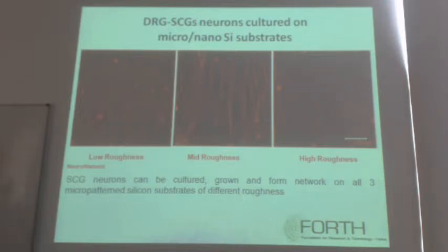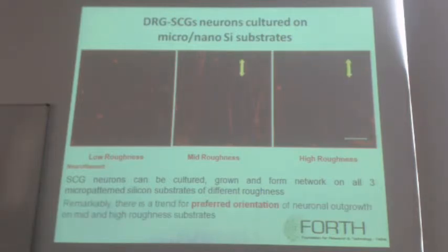So the next step is to culture dorsal ganglia and SCG neurons on top of the structures. You can see here the culture of SCGs on the different roughnesses. As you can see, while in the low roughness there is no preferential orientation of SCGs, you can see preferential orientation on mid and high roughness, and this preferential orientation, as you can see, is directed by morphological features.